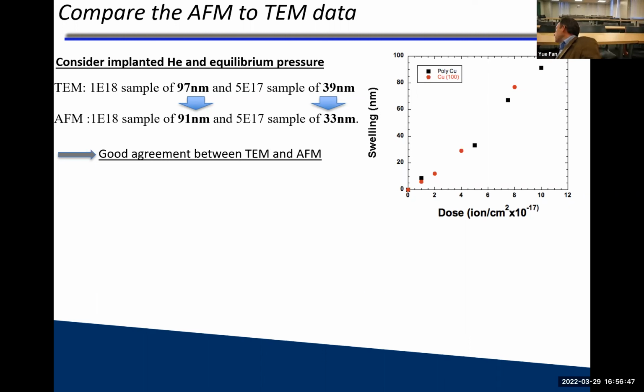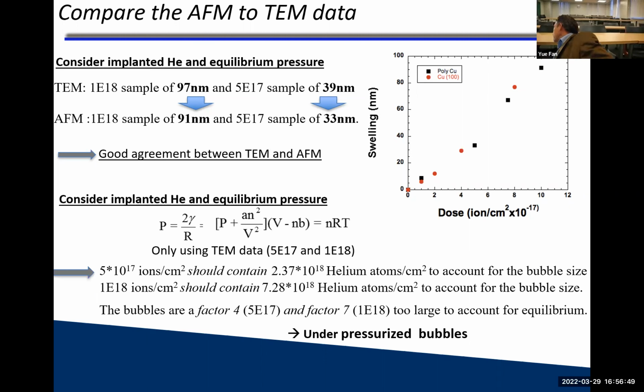And what's the pressure in these things? So you could consider the Van der Waals gas law and say, okay, I know how much helium I pumped in this thing. The helium must still be there. I know the size of my cavities, and how much pressure should be in the cavities by doing so. And what we learned by this is that the sample with 5 × 10 to the 17, for example, should contain actually this much dose based on the microstructure. So we can contain a lot more helium than we actually put in our material.